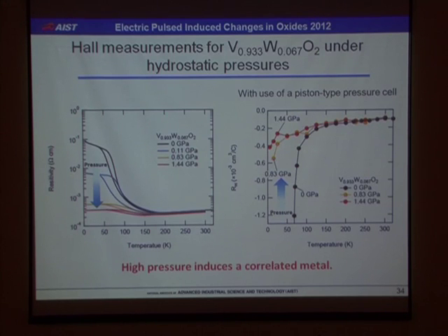And we also performed Hall measurements for the electron-doped VO2 thin film. Actually, here I slightly increased the tungsten concentration because here we use a piston-type cylinder cell. So the maximum pressure is about 2 gigapascal using this system. So this is again the resistivity curve under various pressures, and we can see the insulator-metal transition by applying pressure. And we measured the Hall effect for these pressures. At ambient pressure, dimerization occurs. That's why the carrier concentration is dramatically reduced at the transition temperature. Actually, under high pressures, it has a very huge carrier density, as in metallic VO2. This means that this high-pressure phase is a correlated metal, not a diluted semiconductor.